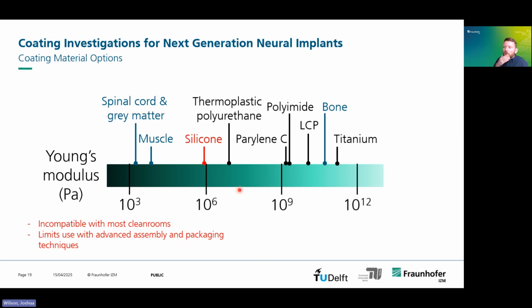Now, what I spoke about so far is only coating the chip, but typically the trend is towards much more complex systems than just a simple chip. And the problem with using silicone is that it's incompatible with a lot of clean rooms, and this limits your ability to use advanced assembly, packaging, photolithography techniques. So if you really want to have miniaturized implants, then probably you're going to need some of these technologies.